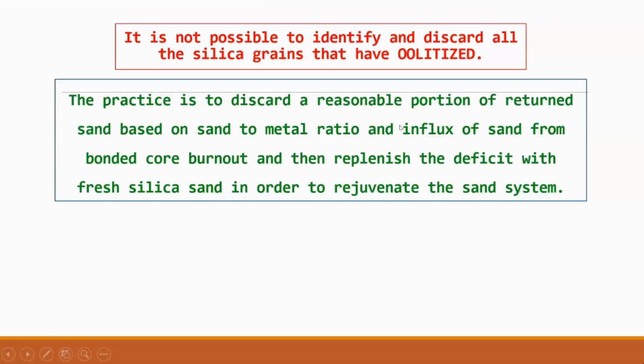You always use sand cores which get burnt out during the pouring and then cooling process, and then some of the sand gets into the system. So that sand, together with the burnout that is going to take place due to the metal that is going to be resident inside the mold, and taking that into account, you have to replenish the deficit with fresh silica sand and rejuvenate the sand system. So you have to discard a reasonable portion. The reasonable portion will vary from foundry to foundry and the product mix the foundry employs and the type of castings you make. And also how long you are going to keep the castings inside the mold before it is shaken out.